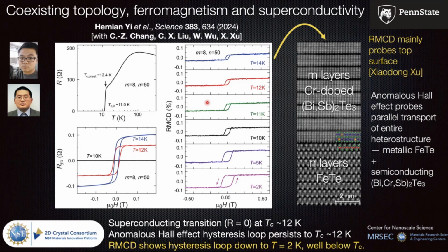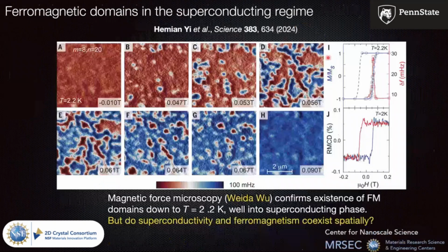With Xiaodong Xu at University of Washington, we did some reflection MCD measurements, which showed that even as you go down to very low temperatures, where the sample is superconducting, you can see an RMCD hysteresis loop. Now, this is, of course, measured at the top of the sample, so presumably the superconductivity is happening at the interface. You're looking at the ferromagnetism at the top of the sample, and you see ferromagnetism well below Tc. And in fact, you can also see this with low temperature magnetic force microscopy, and you can see the existence of ferromagnetism and ferromagnetic domains, down to where the sample is actually superconducting.